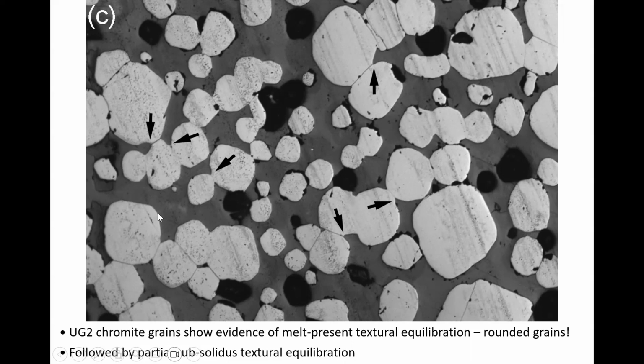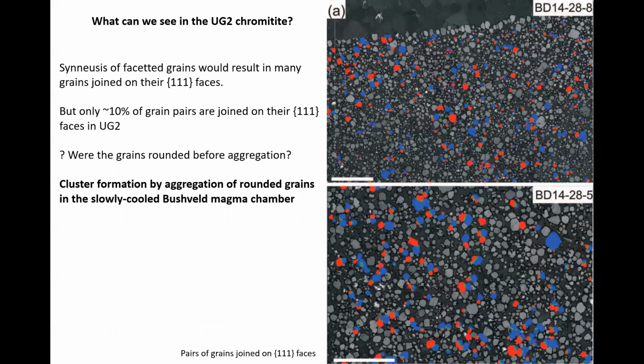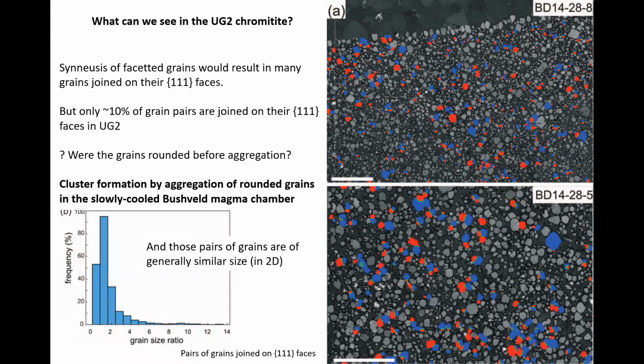So this thing was formed of rounded grains in melt present textural equilibrium. Once it's solidified, you then got some modification. And the fact that we've got this partial subsolidus textural equilibration tells us that it must have cooled really slowly. Subsolidus textural modification takes a long time. So I would argue that the reason we don't see lots and lots of pairs joined by their 1-1-1 faces is because these clusters formed by the aggregation of rounded grains, because we were dealing with a hot system that didn't cool that quickly, and they were texturally equilibrated. They were nice rounded grains. And not only that, but those pairs of grains that we've got are very, very similar in size, and I'll get back to that shortly.